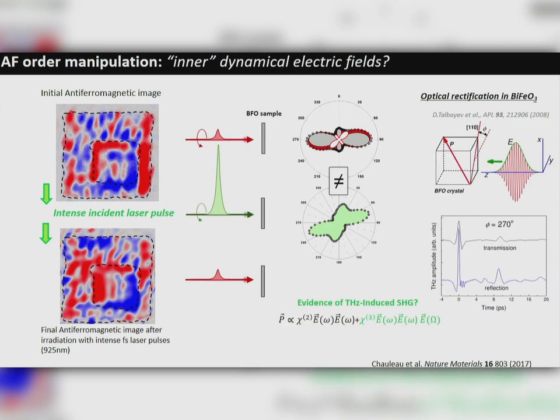What we are thinking is that, of course, bismuth ferrite generates second harmonic generation because it breaks the central symmetry, the inversion symmetry. And if it does that, not only can you do second harmonic generation, but you can do its evil twin, which is optical rectification. Optical rectification is basically generating a small transient polarization while the light is on. And this is what we think happened while changing the antiferromagnetic domains completely.